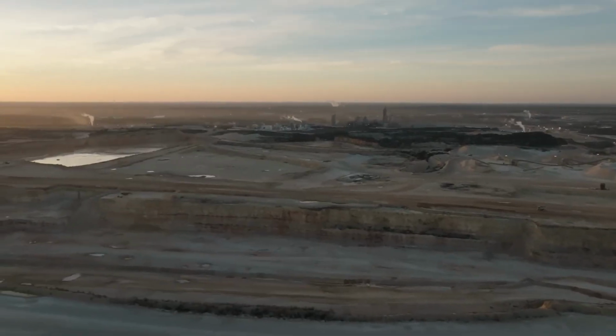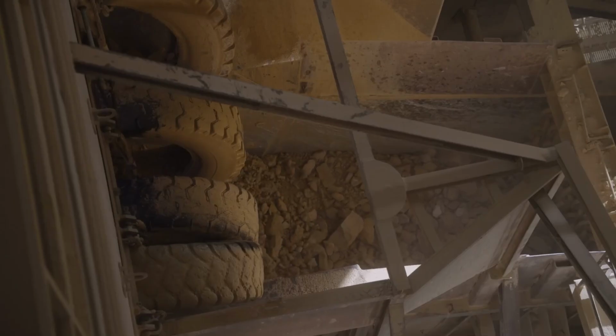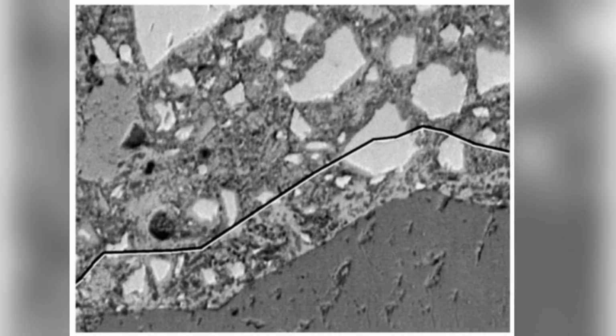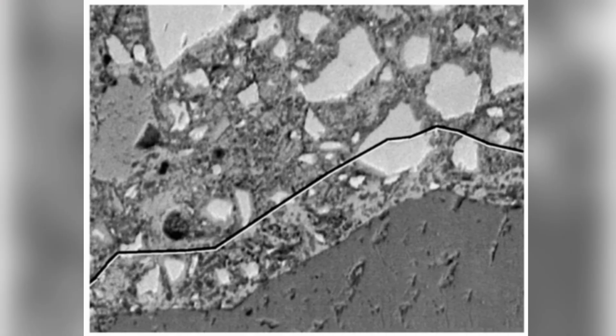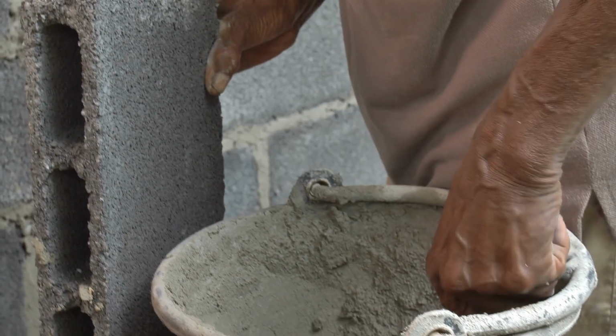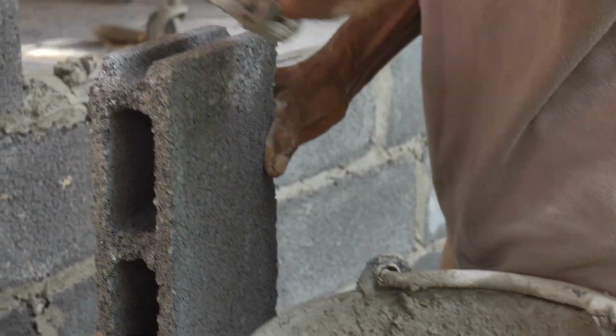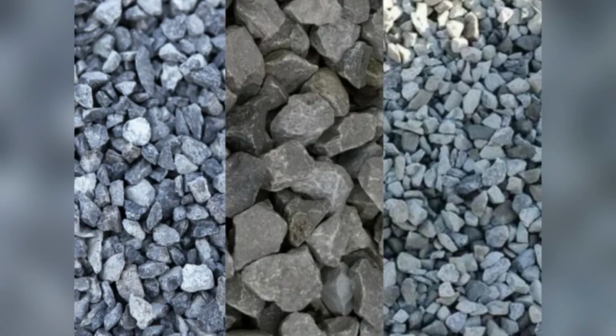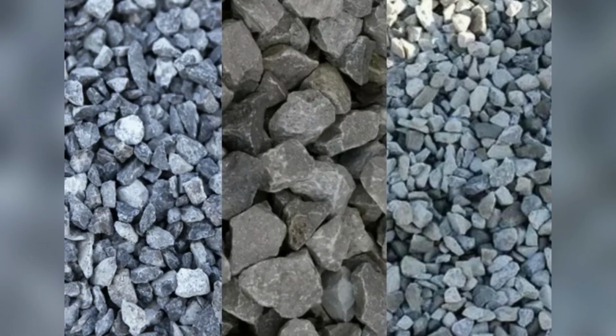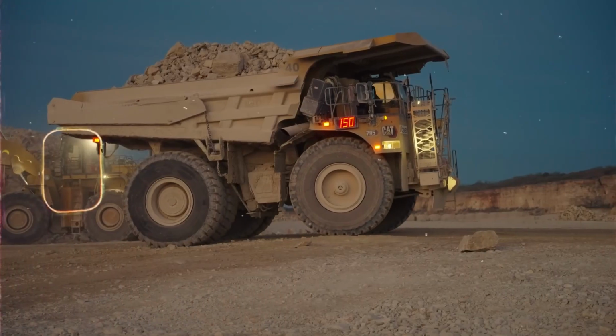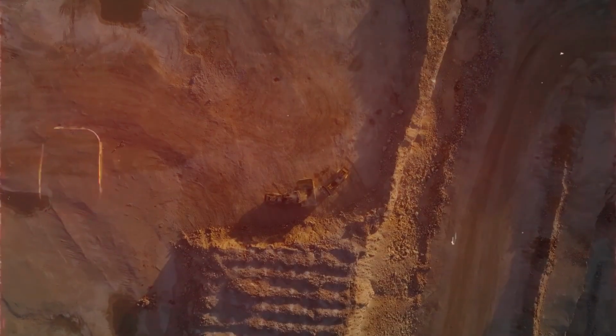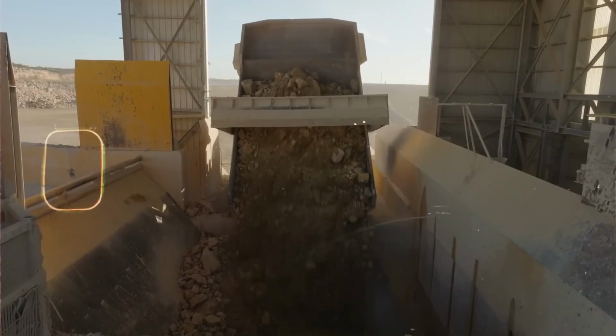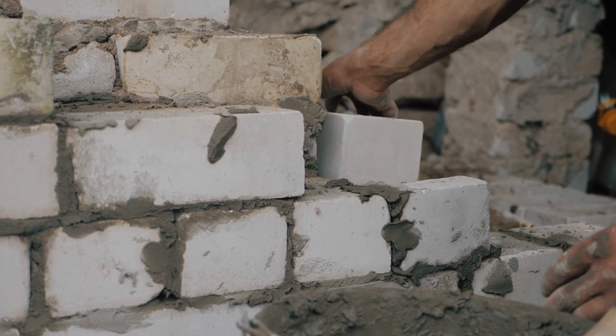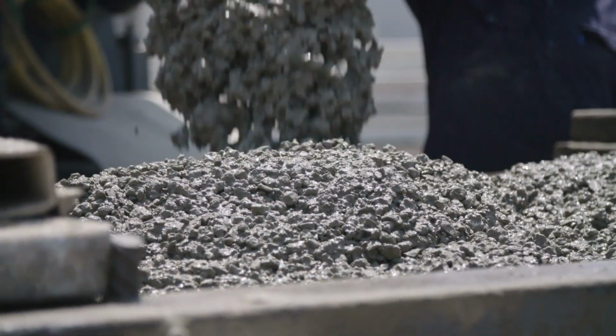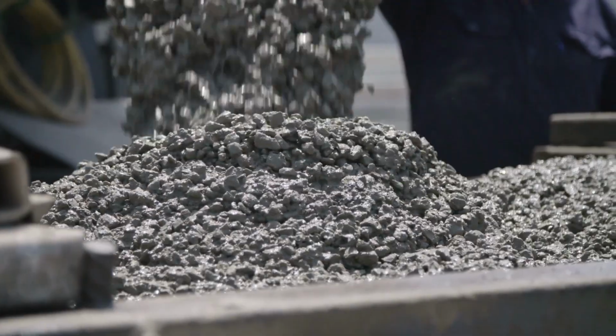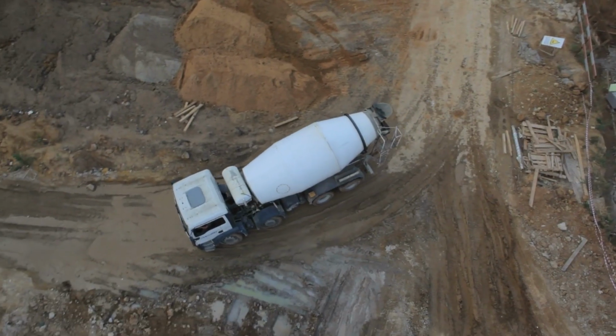But the real magic happened at a boundary you have probably never heard of. Inside concrete, wherever the cement paste wraps around a piece of stone, there is a microscopic transition zone. And in normal concrete, this zone is the single weakest part of the entire structure, looser, more porous than either the paste or the stone alone. It is the first place a crack forms the moment the material is stressed. It is the traitor hiding inside every slab. Under this pressure casting, that traitor zone tightened dramatically, with up to 35% fewer voids than in conventional concrete. The weakest link in the chain suddenly became one of the strongest.